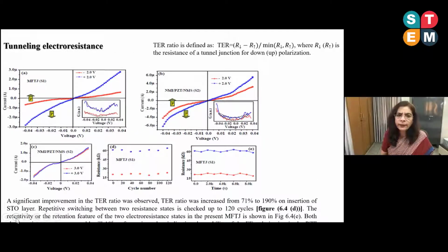Then we tried to measure the tunneling electroresistance, which is defined like this. We observed the experimental IV curve at upward polarization and downward polarization. Upward polarization is like a -2 volt pulse was given while recording the IV curve, and for the downward polarization, a +2 volt pulse was given during the measurements. A large change has been observed in this.